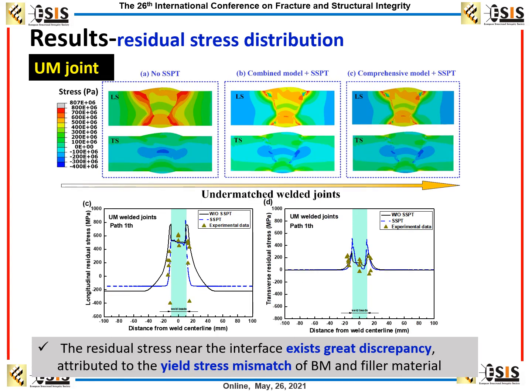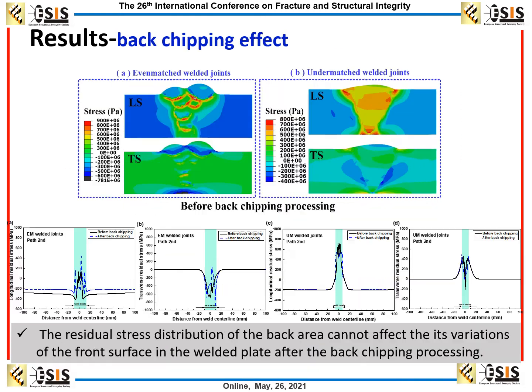This is the undermatched welded joint, considering the SSPT or not considering the SSPT effect. So there are no obvious differences between these results. The residual stress near the interface exists a great discrepancy attributed to the yield stress mismatch of base and filler materials from the figures.